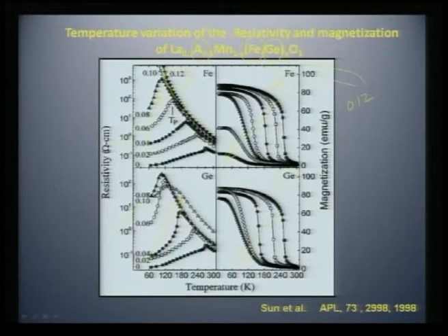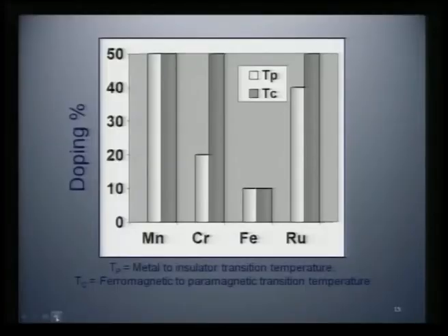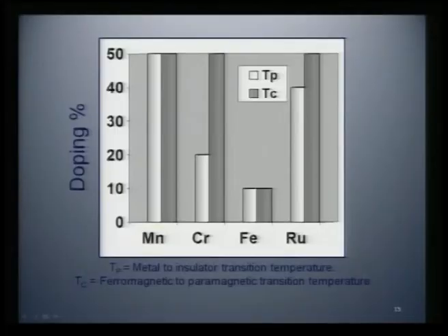So, even in this case, you can see that it happens at 10% of germanium. So, you have either 12% of iron or 10% of germanium totally killing the ferromagnetism and the metal insulator transition. In the next graph, I will show you other transition metals. Suppose it is only manganese, then the manganese 3 plus, manganese 4 plus concentration is like this, and therefore, you can see a double exchange mechanism very strong in manganese.